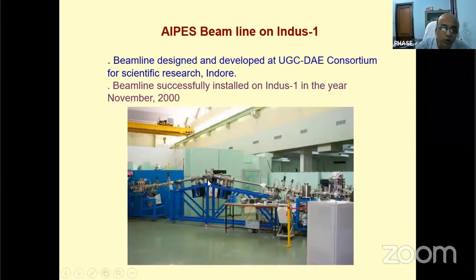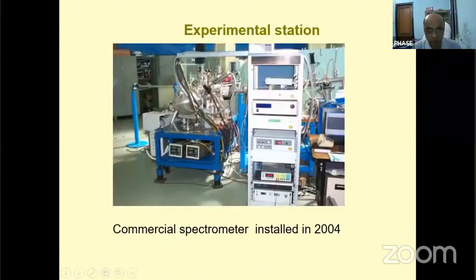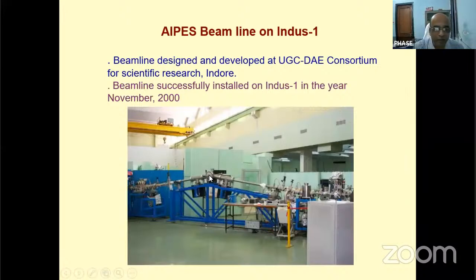And this is our grating monochromator chamber. In this we have three gratings. The beam from the pre-mirror is focused at this slit, and then the beam comes to this grating. So this is the grating chamber, which accepts the beam from the entrance slit. Three gratings cover the whole energy range from 60 angstrom to 1600 angstrom, so three gratings are required: one is 200 lines per mm, then 400 lines per mm, and then 1200 lines per mm.